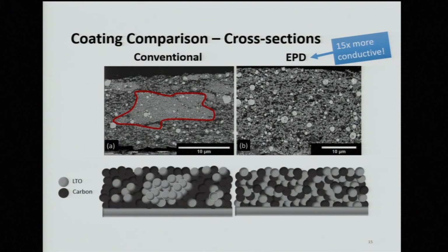Here we have the lithium titanate in gray with the carbon in black. Remember how I said that the carbon improves the conductivity of the overall material? It sort of acts like a highway for the lithium ions and the electrons to flow through. For this material to perform, the lithium ions and the electrons have to reach the surface of the lithium titanate to react. And when lithium titanate is in contact with carbon, this happens very fast. But what about this middle lithium titanate?